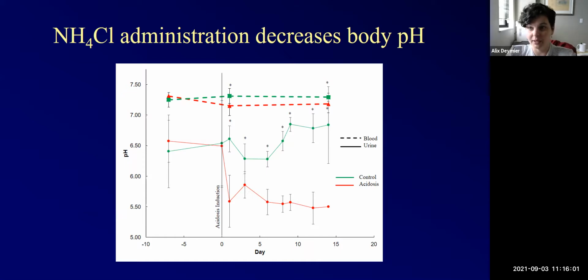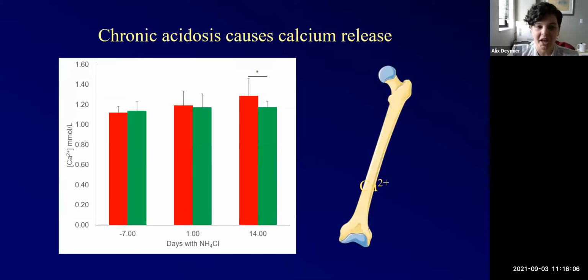Now, what does that mean? If we keep looking at the blood, we see that at one day, the calcium levels in the blood are pretty much unchanged. But at 14 days, so 14 days of drinking soda, the calcium level in the blood is significantly higher than in my control mice. So what this tells me is that high calcium is probably coming from my bones. I probably have some level of calcium being extracted from the bone and put actually into the blood supply.